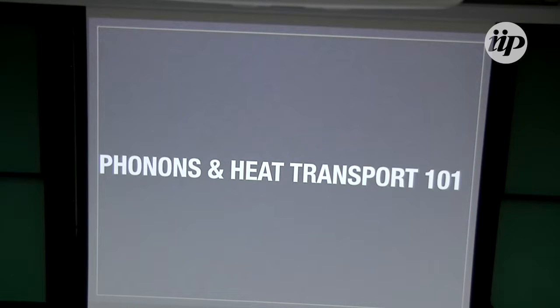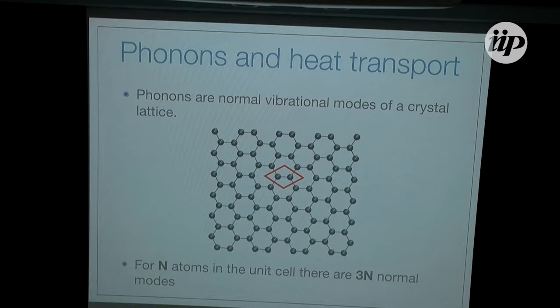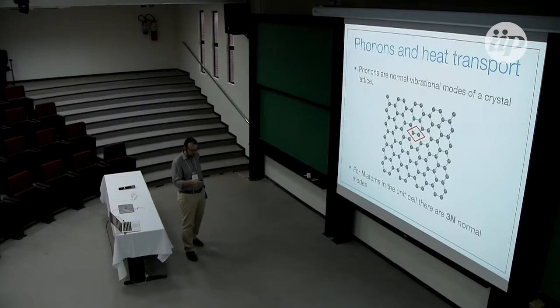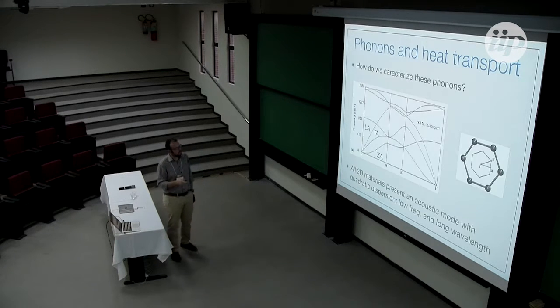So let me show you a couple slides about phonon heat transport. People have already done pretty good work about this today, just to show specifically how it would work in a material like graphene. So in graphene, you have 2 atoms in your unit cell. And if you have n atoms in the unit cell, there are 3n phonon modes. Phonons are these vibrations of the lattice, right? This would be a picture at 0 Kelvin. When you have finite temperature, all of these atoms are vibrating, but they don't vibrate randomly. They vibrate in some sort of collective modes. That's what we call the phonons.